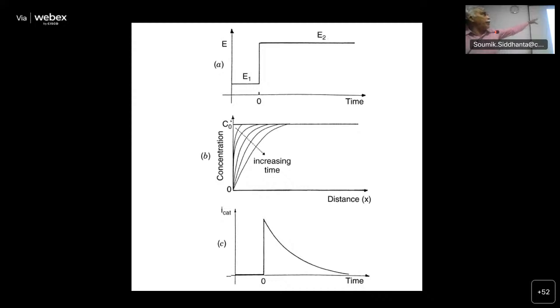Now, you can see what happens. E1 is the initial value, E2 is the final value. So I am applying a step from E1 to E2. What happens? The concentration of initial C0* is the surface concentration. As a result of the reaction, slowly the buildup of the layer happens, the diffusion layer. That is, the time is very important. How thick the diffusion layer can form, we can calculate. This is called Nernst diffusion layer thickness. If I know the diffusion coefficient, I should be able to calculate how much time it takes.